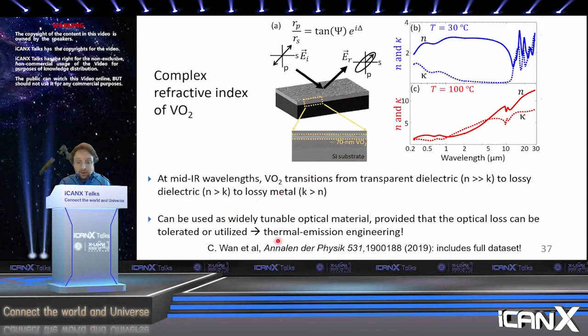And therefore, it has all of these potential uses as a tunable optical material, provided that the loss that's present can be utilized. But one thing that we found that was quite exciting is there is a special region between about 2 microns and 11 microns, away from interband resonances and also vibrational resonances, where the losses in at least the insulating state are quite low. And so you can use this material even for some more conventional type of optics, not necessarily even thermal emitters. As long as you're within this wavelength range, you have at least one phase that's relatively low loss, and therefore, you can use it, for example, for transmission type optics.